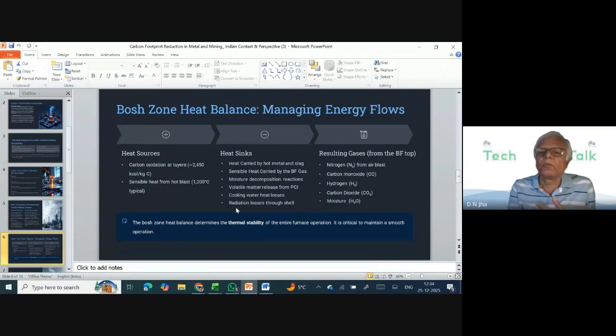So we did talk about all the gases. At the top, we have nitrogen, we have CO, we have CO2, because the CO, after the reduction of the oxide, once I say oxide, that means Fe2O3, which we are charging, whether it is in the form of sinter or pellet or the sizer, that is having predominantly Fe2O3. Once it gets reduced, and it is getting reduced by CO, there would be CO2 there.